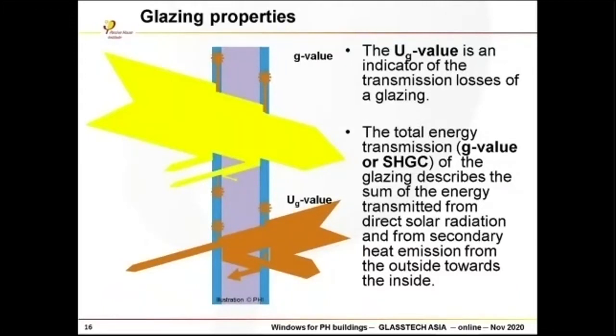You all know we get solar radiation from outside through the glazing to the indoor, to the room. And the solar throughput is described by the G value. The higher the G value, the better. And second, in wintertime especially, we have thermal losses. So energy, thermal, temperature going from inside to outside. And the U value describes these thermal losses. Okay, so we have to set up a very good, the best ratio. So the lowest U value and the highest G value, if possible, to get a good performance window.